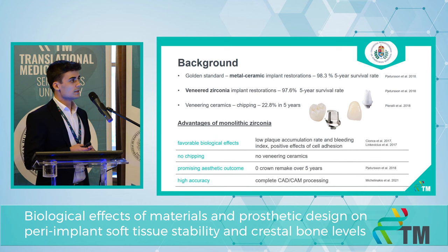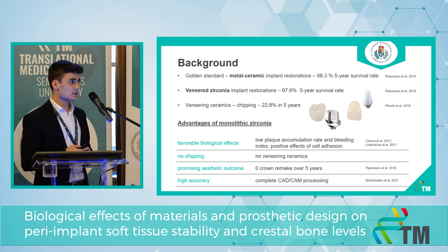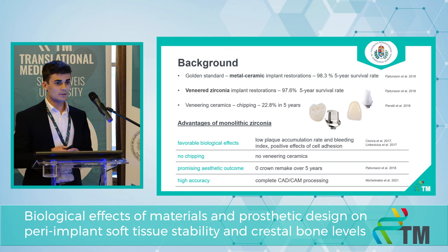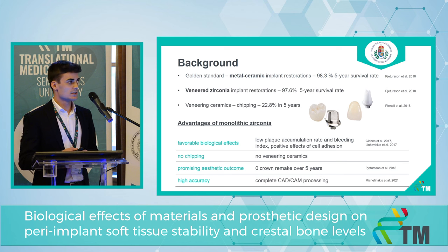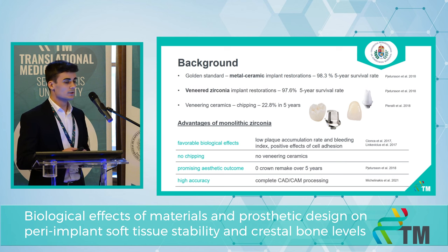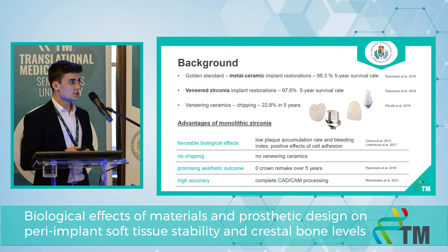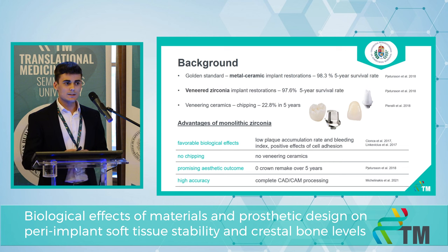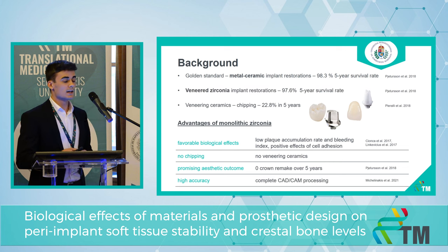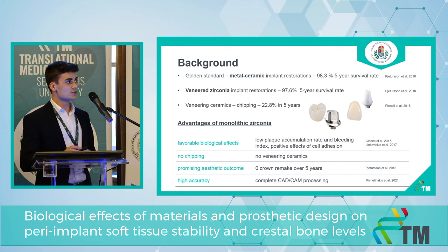Monolithic zirconia without veneering ceramics has several advantages. Its biological effects are favorable because it has a low plaque accumulation rate and bleeding index, and also a positive effect on cell adhesion. Since it has no veneering ceramics, it will not chip. It also has promising aesthetic outcomes, and because of its CAD-CAM processability, it offers high accuracy and time efficiency.